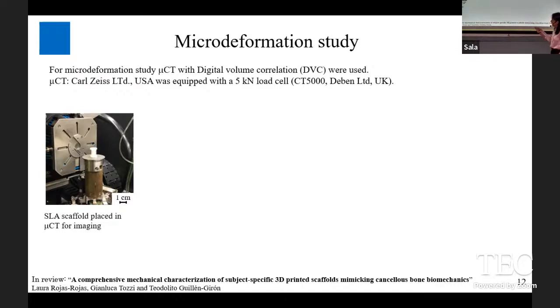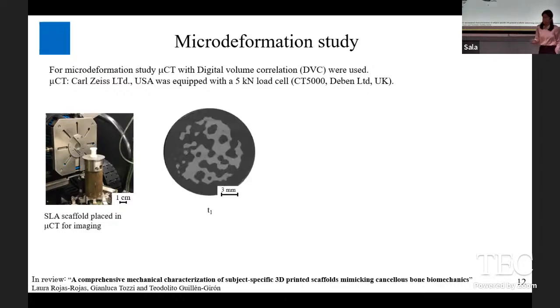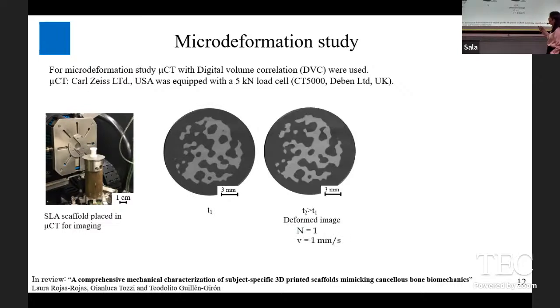Over here is where X-rays are emitted. Now, high energy X-rays go through the sample into a detector, and these are captured according to the density of the sample. So, as an example, here is a cross-sectional image of how an image is acquired. The light gray areas are where the scaffold is, and the dark gray areas is where the air was. Remember, this is a technique that is used in 3 dimensions, but here I'm only showing 2 dimensions.